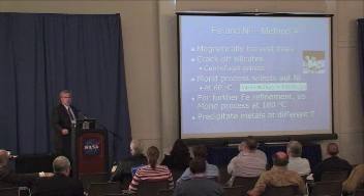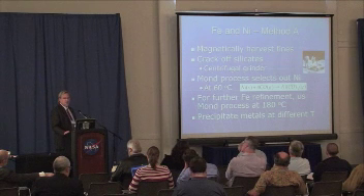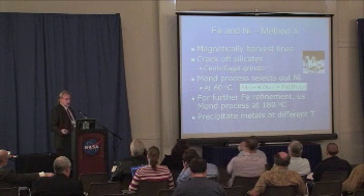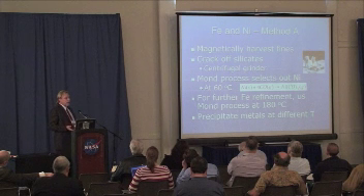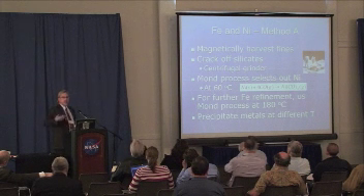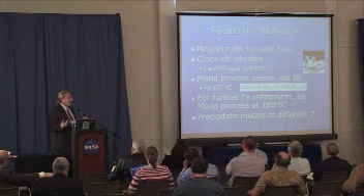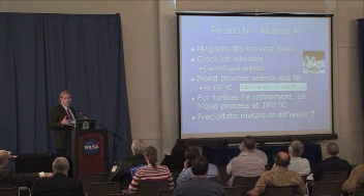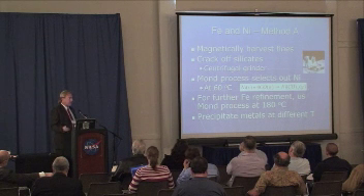Then the Mond process, which was invented over 100 years ago, is to use carbon monoxide to dissolve these metals. So we make this very toxic material called carbonyl, which has a very cool property of being a gas that we can heat up and then cause to precipitate out. Because iron and nickel have different temperatures at which they form carbonyls, once those precipitate out, we can use fractional distillation to get these 2 different metals out.